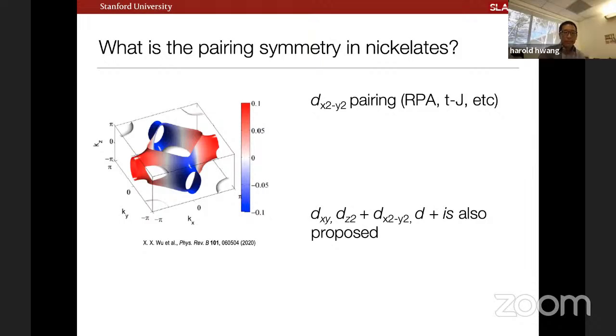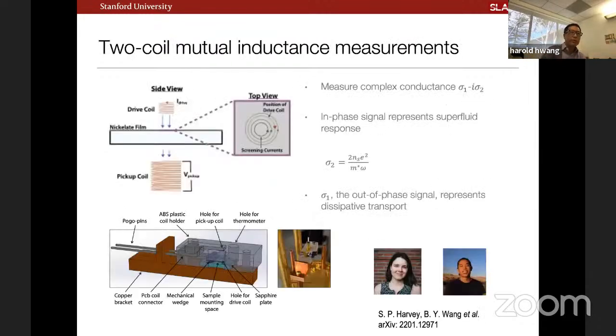So, right. These questions were around, as well as an STM study that suggested that both V-shaped and more fully gapped-looking structures could be observed in spatial variations. And so we were interested in trying to go after this using two-coil mutual inductance measurements. We have the challenges again of being in this thin film geometry. And a lot of what we built was some version of the approaches taken by many groups, but also Bozovic's group at Brookhaven, in terms of having a drive coil and a pickup coil in order to directly measure the complex conductance.